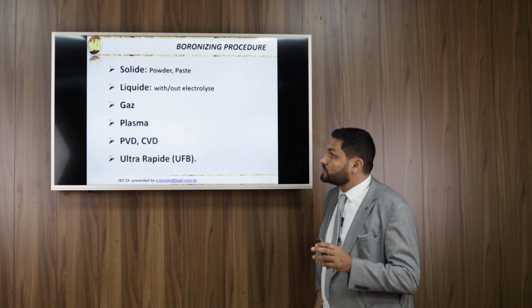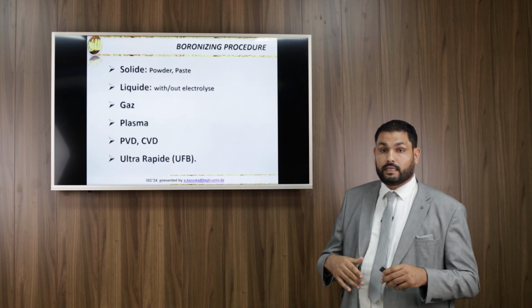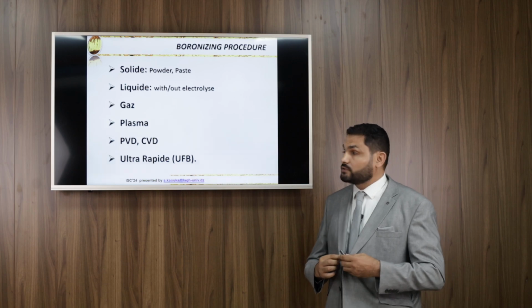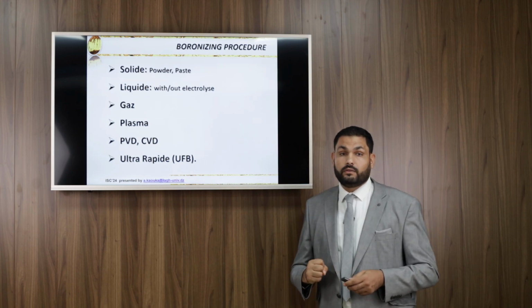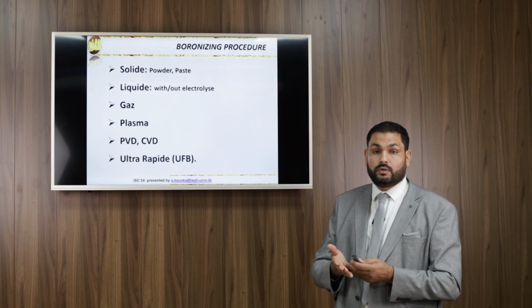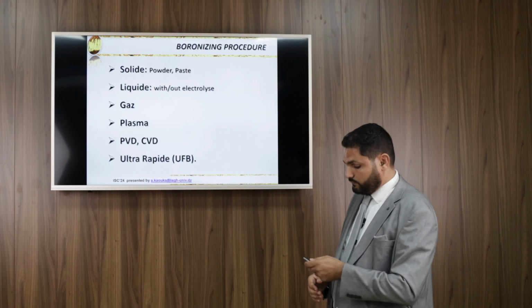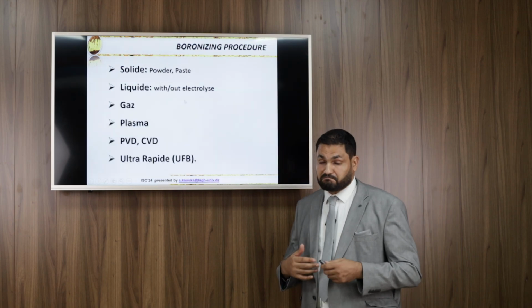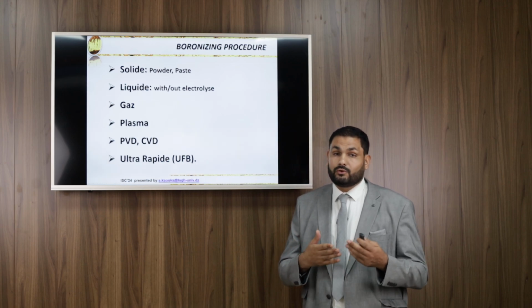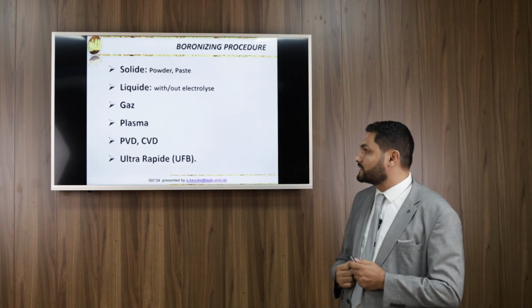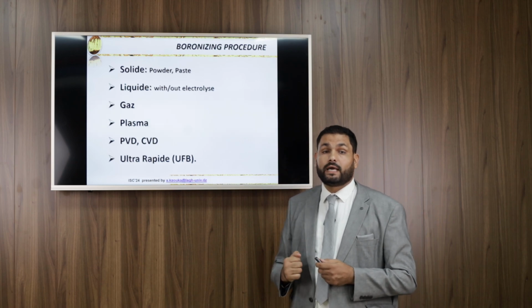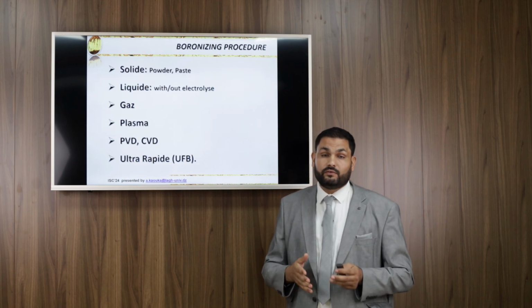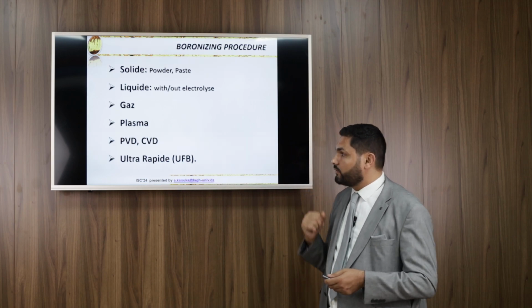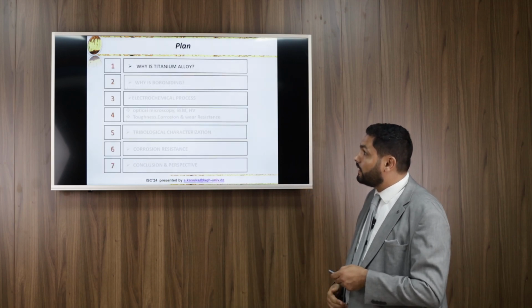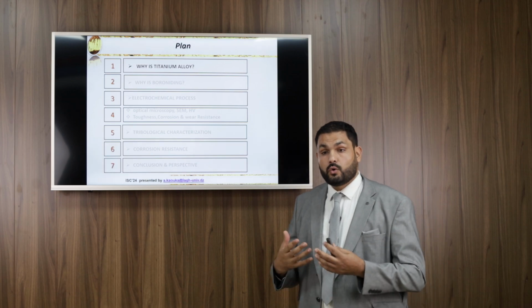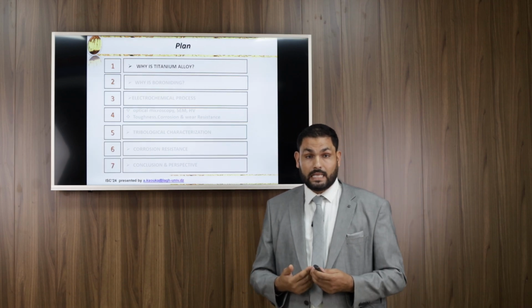So we focus on solid because this is classic and very easy to achieve in industry. For liquid, the inconvenience is that the samples that we obtain are not clean. And for gas, usually we use toxic gas, so we avoid this process. And plasma-fast boriding is also interesting. However, it's more expensive than other processes. So for our treatment, we choose solid boriding.